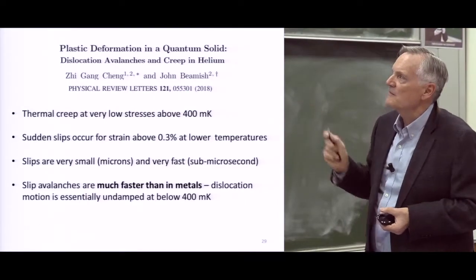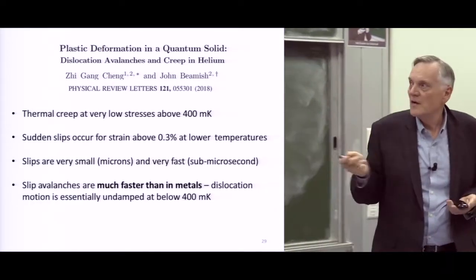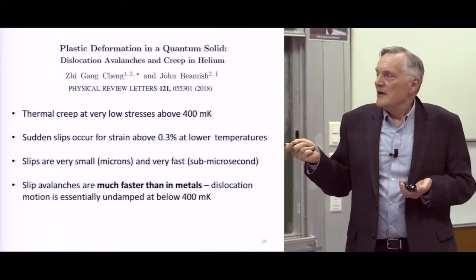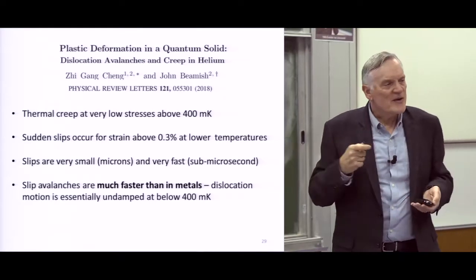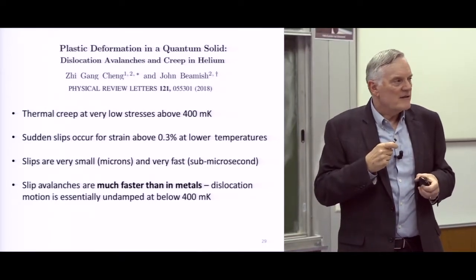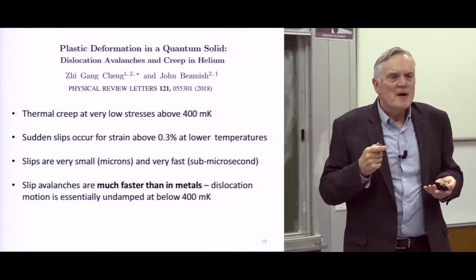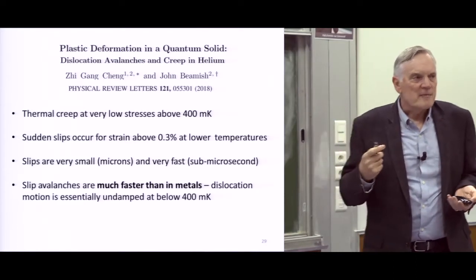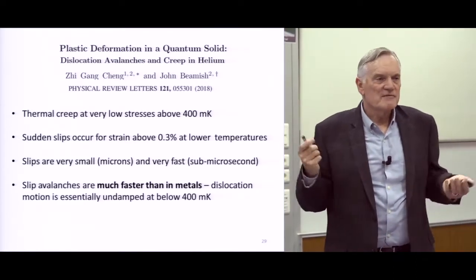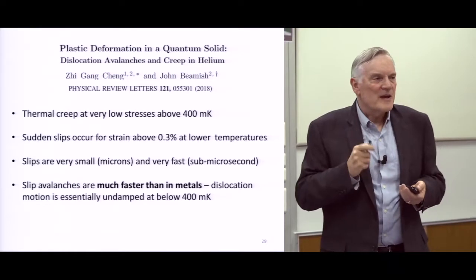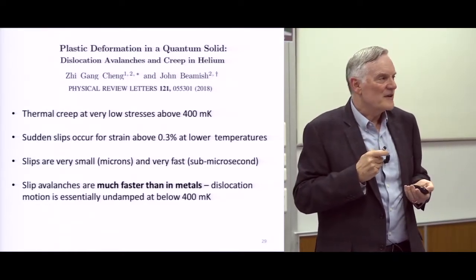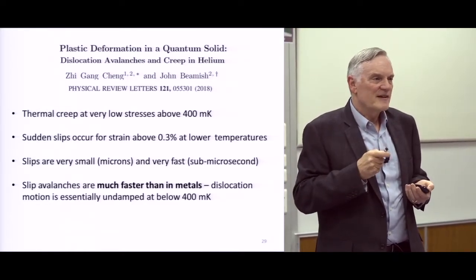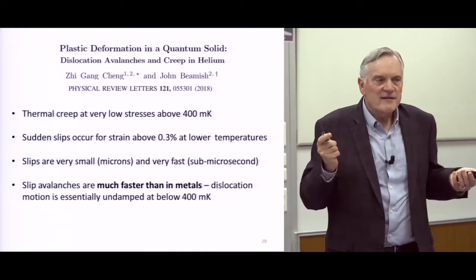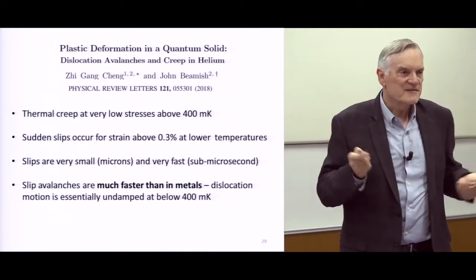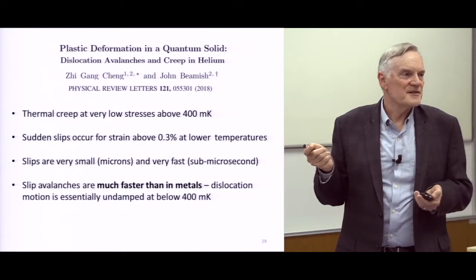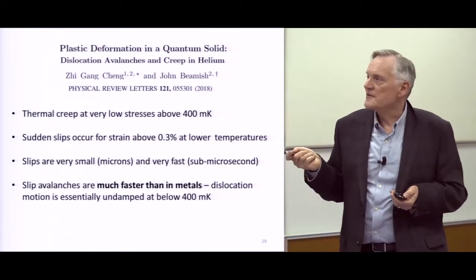This paper on plastic deformation was published a few months ago, if you want more information. It's interesting that even in a metal you can get dislocation avalanches, and you can deform something incredibly rapidly, even explosively in a microsecond. You still can't make those dislocations move as fast as they move in helium, because they're always damped by something. In helium, at low temperature, there's nothing left to damp them. They move virtually at the speed of sound, which is essentially impossible in conventional materials.